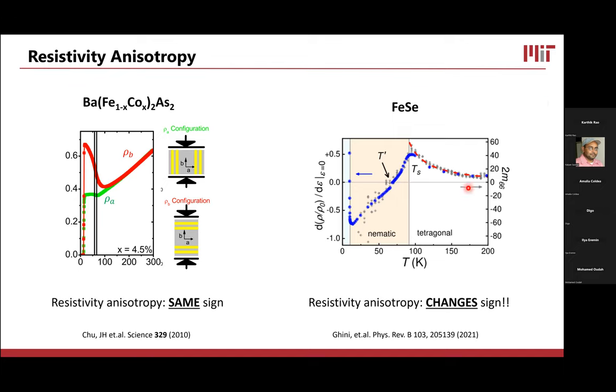In iron selenide, something pretty unusual happens. If we look at the resistivity anisotropy above the transition, it's initially positive, and that's fine. Some of the pnictides are also positive. It shows a divergence towards the nematic transition, and that's great. The pnictides also do that. So that indicates that this nematic transition shows the same kind of electronic driver as in the pnictides.